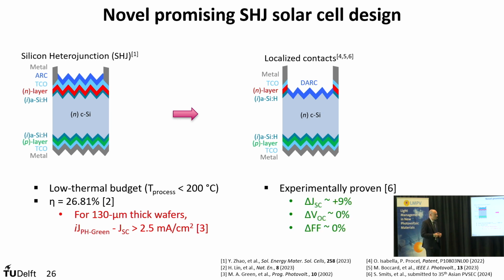The results will be presented this autumn in Japan at the Asian PVSEC, but I can already mention that we are extremely happy that with today's crystalline silicon wafer quality, we can essentially keep VOC and fill factor unaltered after all processes, and actually boost the short circuit current density by at least 9% with respect to the reference with the layers deposited over the full area.